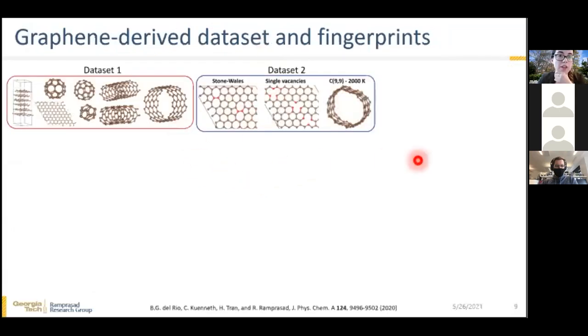So to first develop the entire protocol, we chose a data set containing just one single element, but diverse enough. So in our case, we chose carbon, and as the structures, we went with graphene-derived allotropes. Also, we created two different data sets to test the transferability of the model, two configurations which contain defects and also higher disordered structures. Additionally, to have a large amount of configurations of each structure, we perform molecular dynamics simulations at 300 and 600 Kelvin, and then chose 200 random snapshots from it.